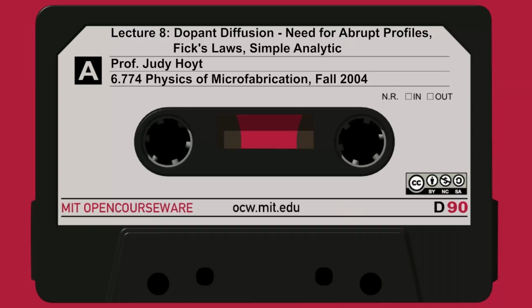Essentially what we see is that the flux F, moving in this case to the right, is equal to minus a constant called the diffusion constant times the gradient dC/dx. So as you take the slope along that curve, wherever the slope is very steep, you get a large flux and therefore a large movement in the profile.